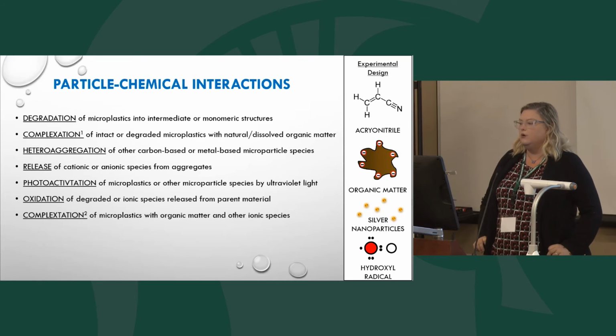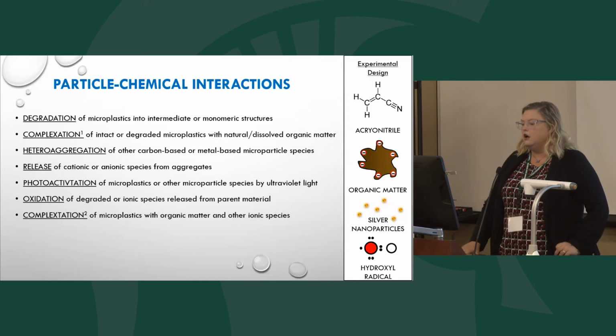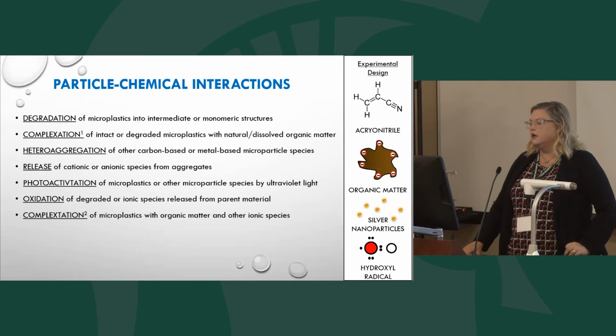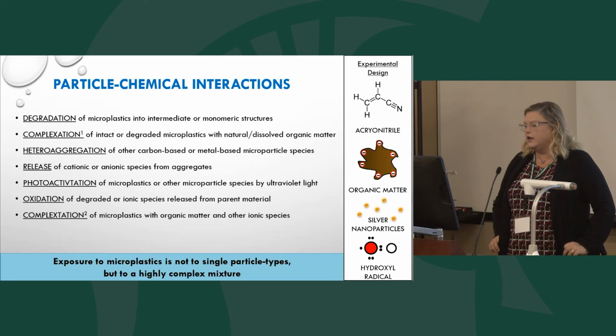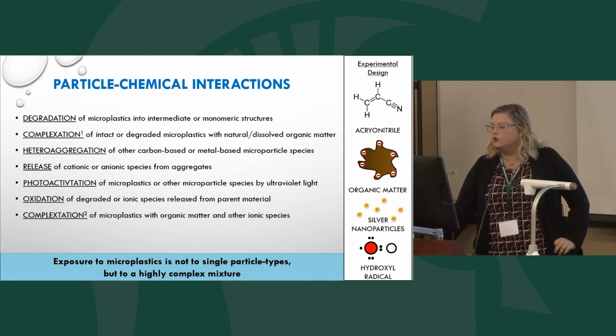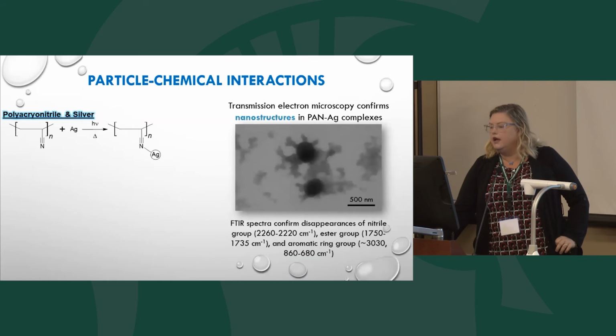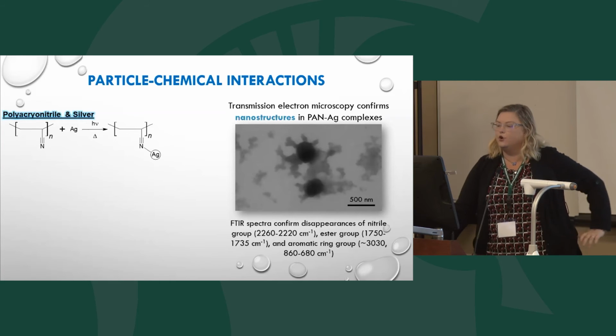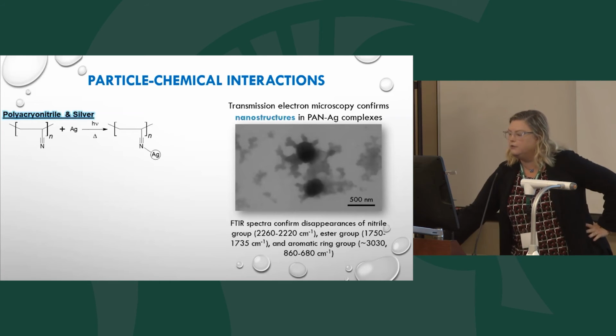We ran one study where we actually incubated a PAN, polyacrylonitrile, with organic matter and silver nanoparticles together to be able to produce some studies. Here is the TEM image of those silver nanoparticles. The darker spots are silver nanoparticles here in the middle. And this is what's presumed to be the natural organic matter and the PAN particles. The transmission electron microscopy confirms nanostructures in this particular complex here.